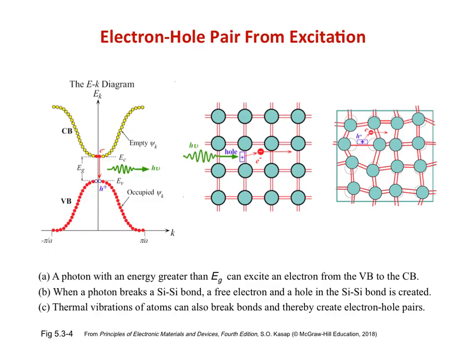In a semiconductor, an electron and hole pair can be created by a photon or thermal excitation of an electron across the band gap. At a local level, we can think of this as the photon breaking the bond, moving the electron out of the bonding network into the conduction band where it behaves like a free electron. For thermal excitation, we can think of the motion of the atoms as stretching the bonds, which will sometimes break a bond. This removes the electron from the bonding network and allows it to transport freely in the conduction band.